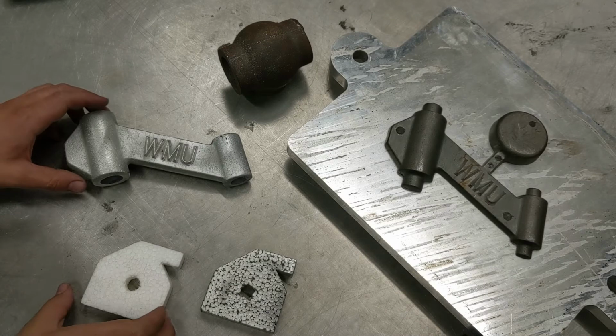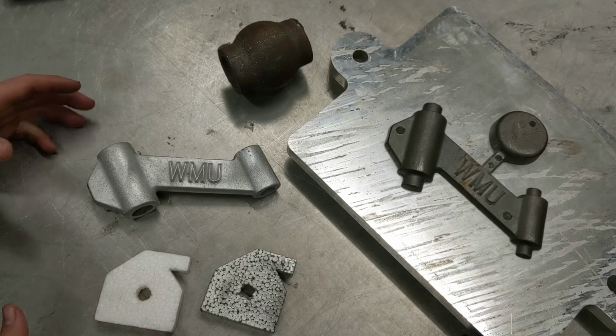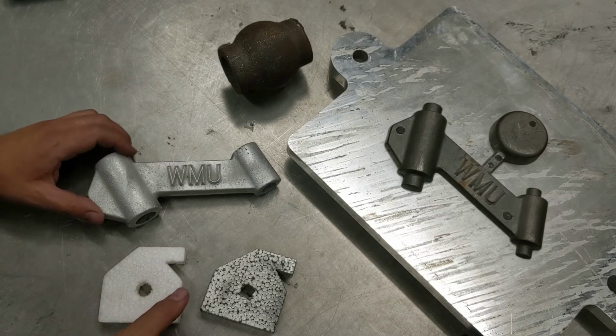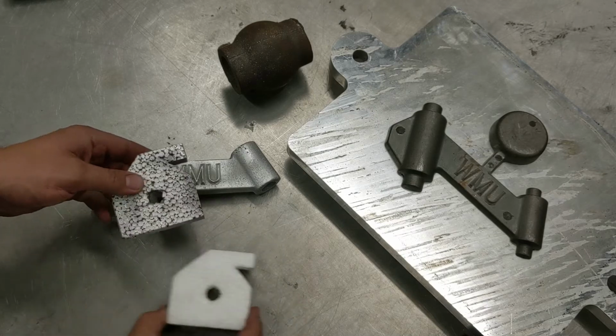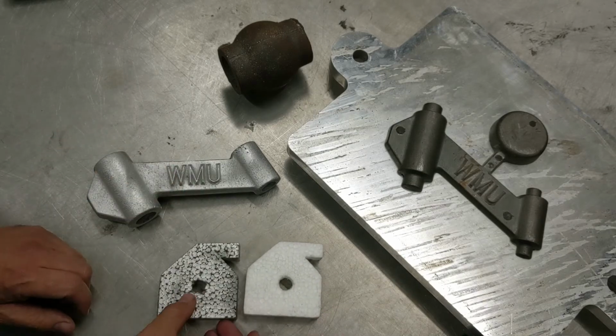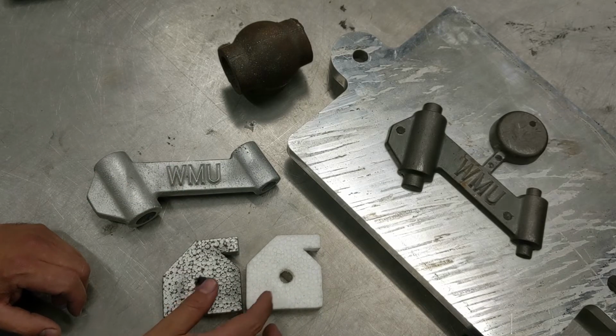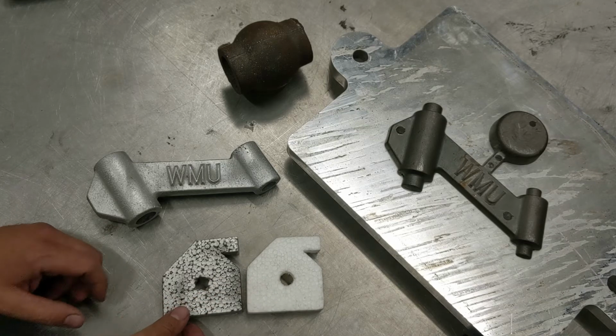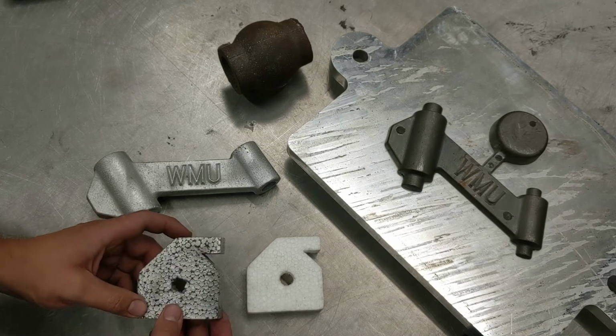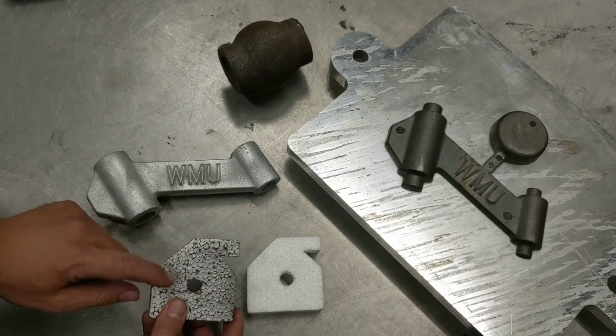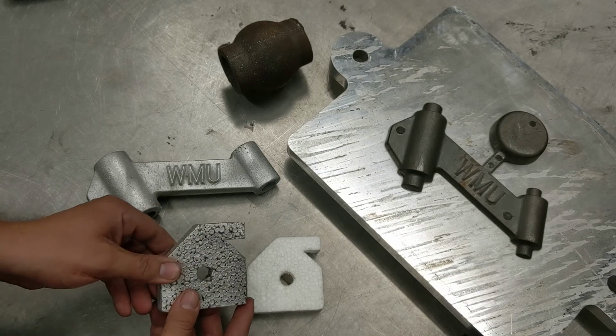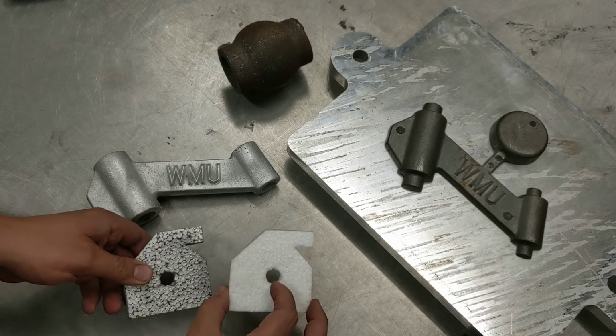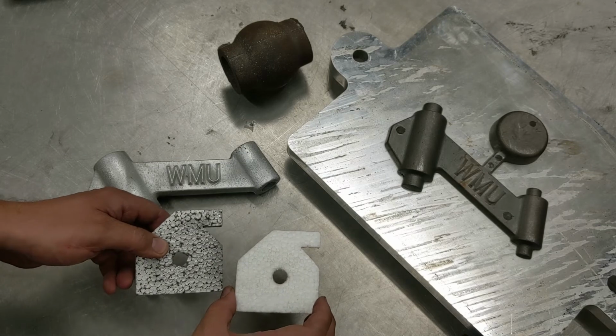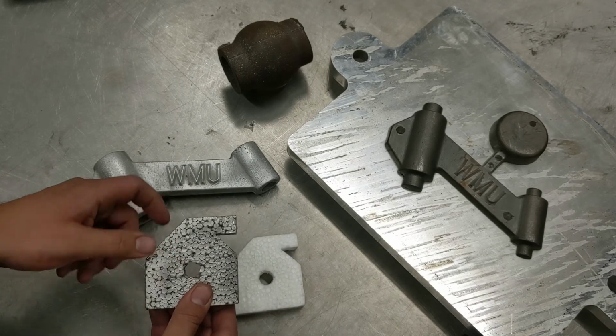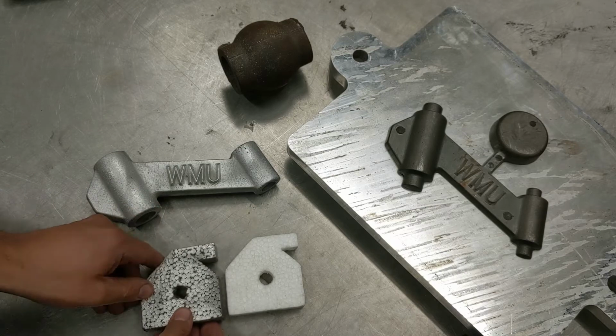All right, as we wrap up this activity, we're just going to look at the castings that we made. The lost foam casting wound up having a really excellent duplication of the surface finish from our original part. There are a few defects that we see here, mostly around the hole in the middle. That's because when we cut a hole in the polystyrene foam, we used a twist drill, and it tended to tear out some of the pellets of polystyrene foam.